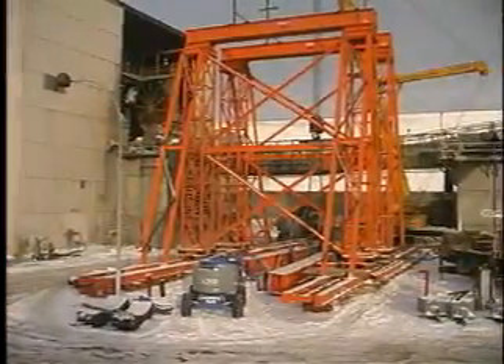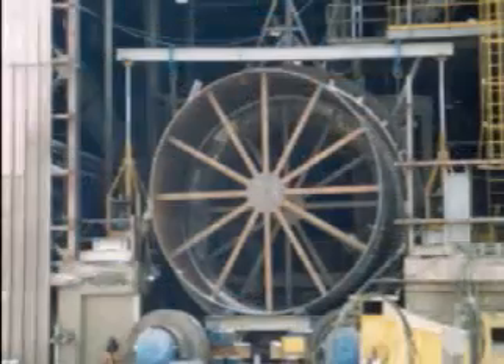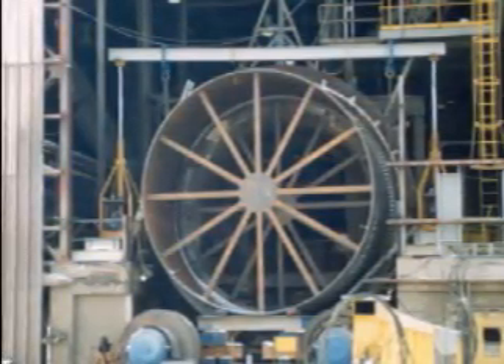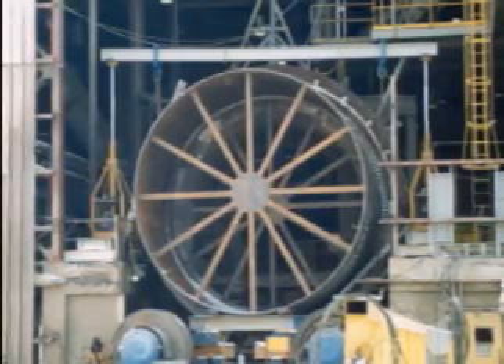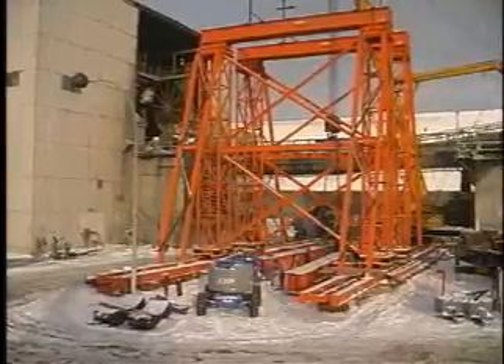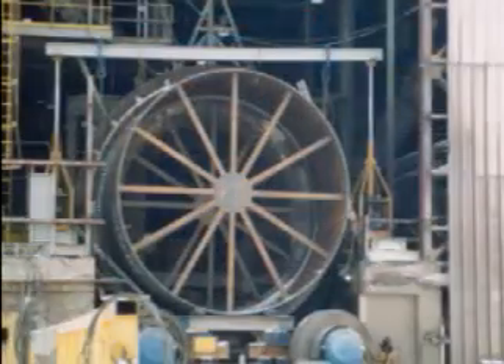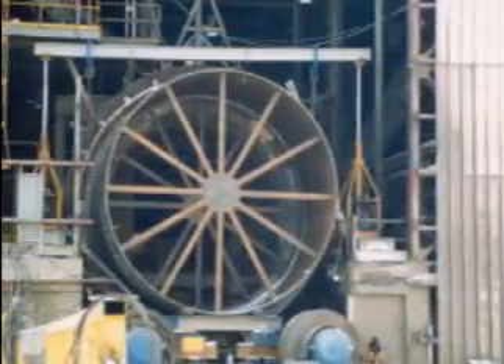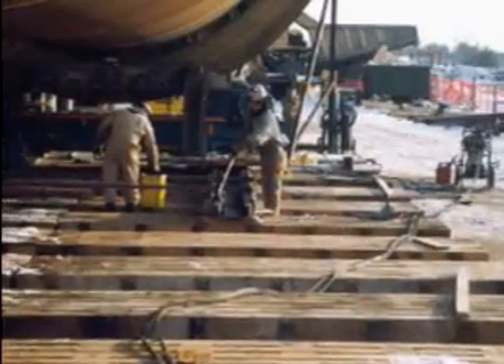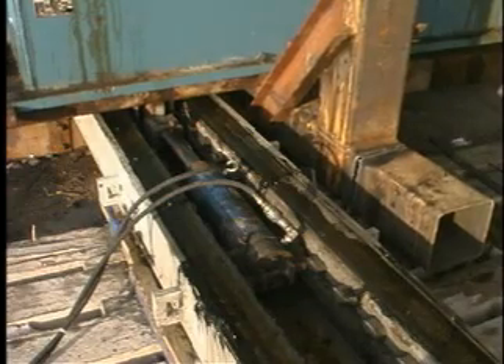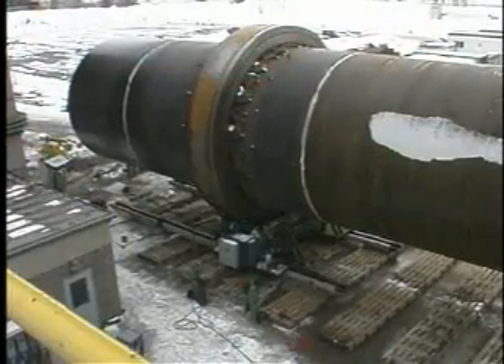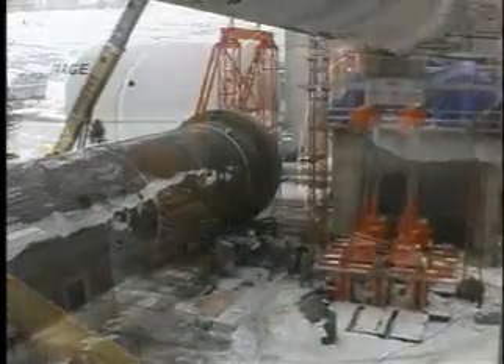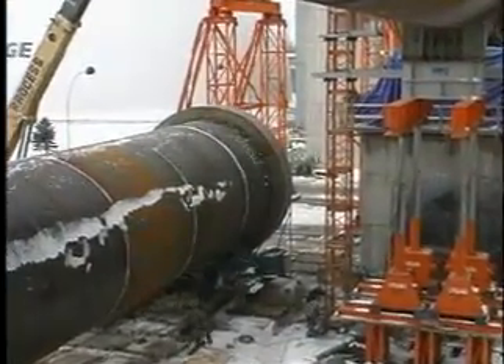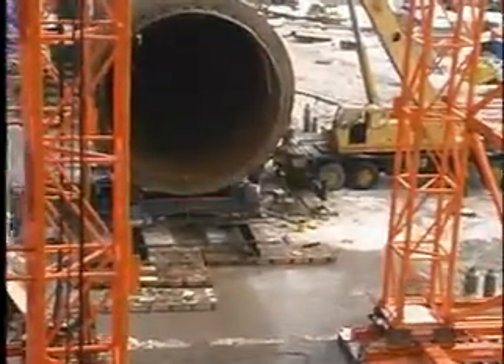The final demanding exercise was the erection of the replacement kiln assembly, which began with the placement of a new kiln outlet section inside the burner building using a 250-ton Krupp mobile crane. Again, the 40-ton gantry provided temporary support, and the spider bracing kept the shell round throughout the handling and assembly process. The PMI 400-ton per pad capacity skidder track was already under the kiln tire turning fixtures. The hydraulic skidder system was then employed in a leapfrog manner over leveled crane mats to move the 650-ton kiln assembly parallel to the existing kiln shell, approximately 150 feet, to achieve proper placement under the lifting tower.